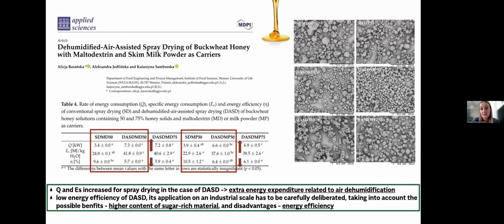So definitely these parameters such as energy consumption and specific energy consumption, in the case of DASD, we observed the extra energy expenditure, which was related to the extra unit for air dehumidification. And especially for the implementation in the industry on the industrial scale, the application has to be really carefully deliberated because we can observe the low energy efficiency, but at the same time, we know that there are very important benefits such as increasing the content of this raw material in the powder, so increasing as well the antioxidant activity of the powder and its potential in bioactive compounds. But as the disadvantages over here, you can see the energy efficiency is quite low.